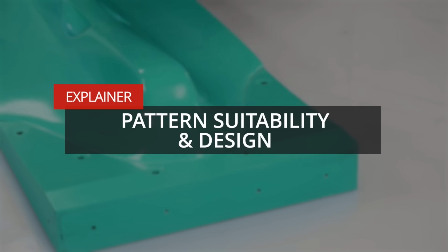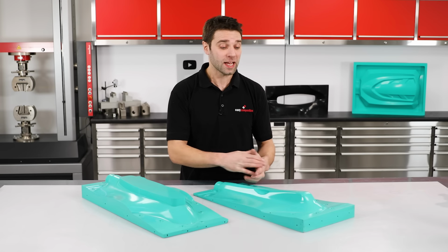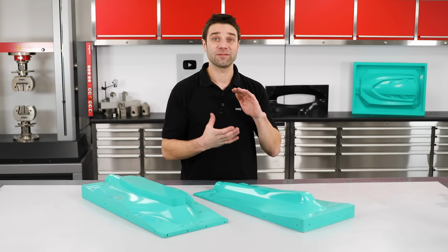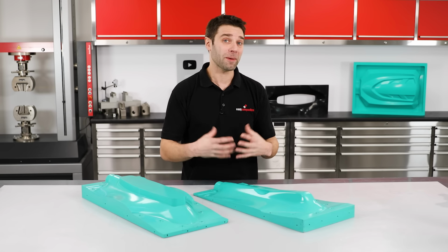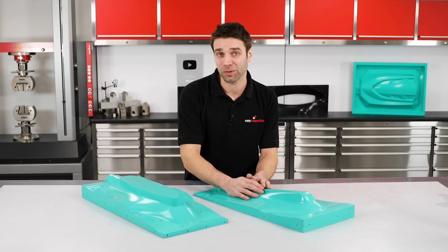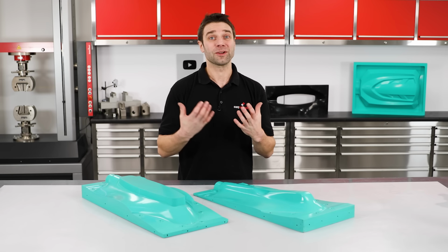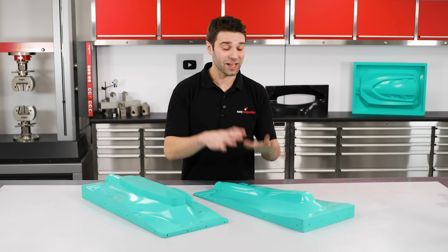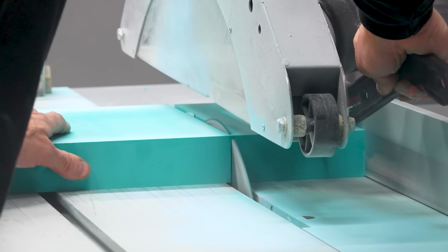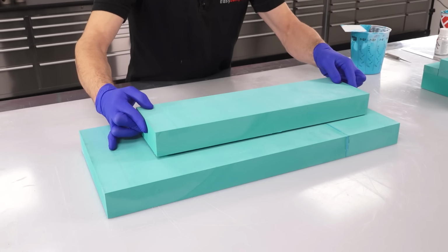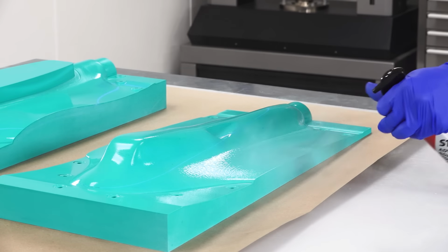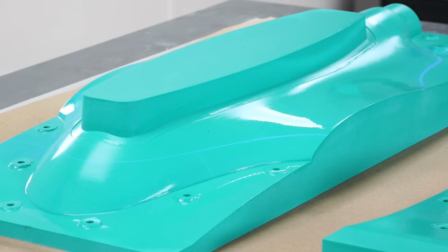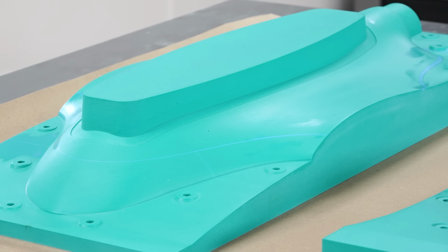Firstly, let's look at the patterns. These are used to form the molds. As tooling prepreg requires an elevated cure temperature, the material that you make your patterns from must also be compatible. Normally, that's going to mean that you're going to make them from epoxy tooling board like we have here. These patterns have been blocked out with EB700 epoxy tooling board, then CNC machined on a 3-axis router to final shape, had any machining marks removed by hand before being coated with S120 board sealer to get us to the final finish patterns that you see here.